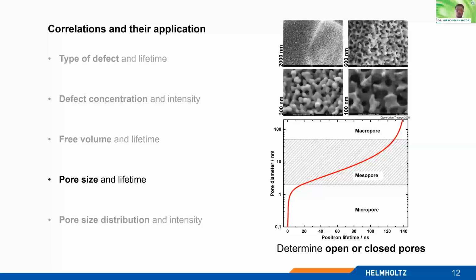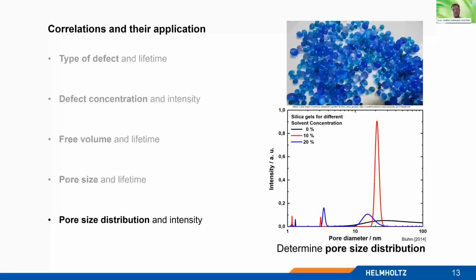And even if you have a closed pore system, which is hard to investigate with gas sorption or mercury intrusion, then you can also use this tool, because positrons have no problem with walls, so they can also enter the closed pores. And the good point here is, if you have a porous system and would like to investigate the pore size distribution, then you can do this with positrons as well, just by using the positron lifetime distribution and then calculating from this the pore size distribution and their fraction within the material.